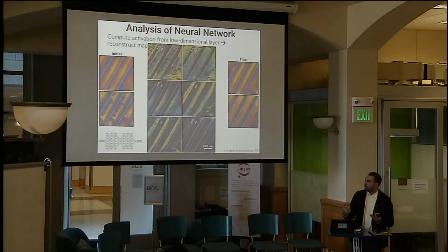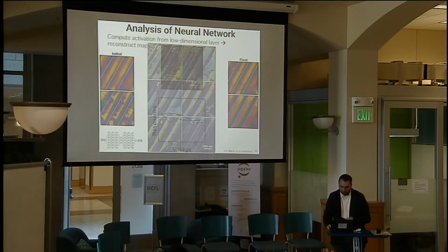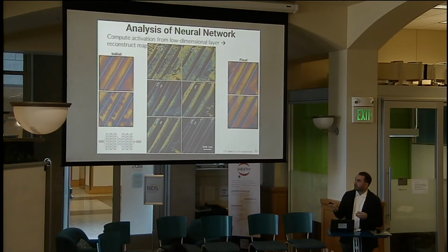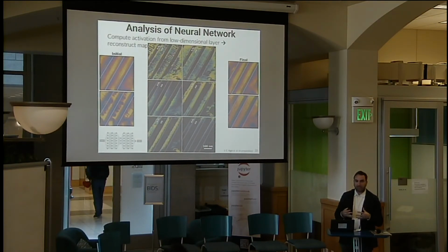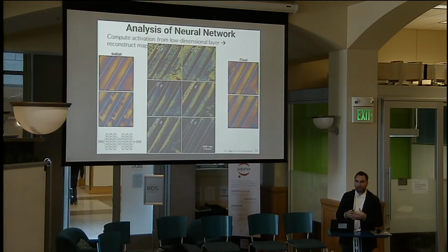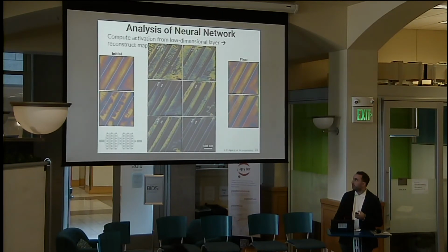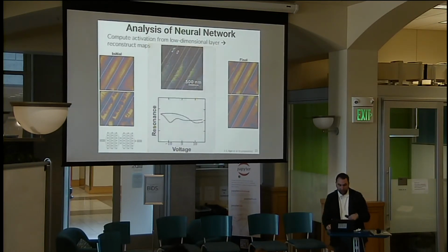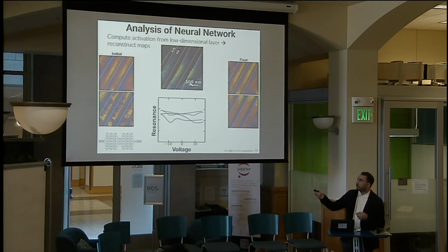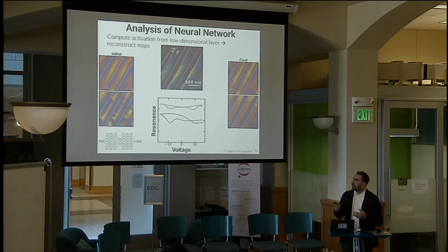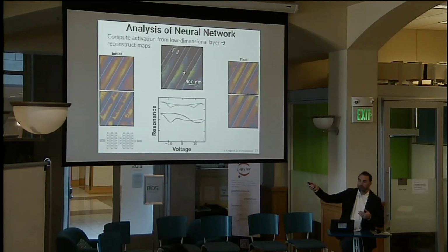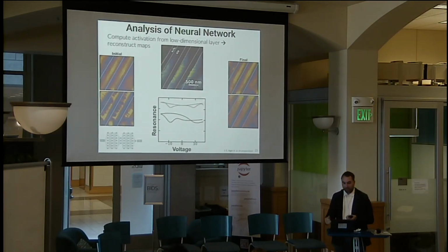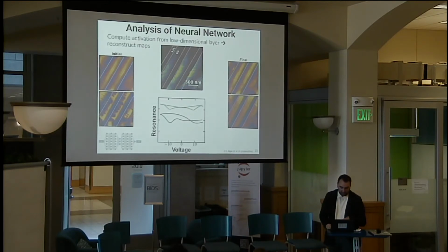I also went on to train this on a more complicated data structure. So this is the resonance response curve, which has a complexity in terms of its functional form that's too complex to even try to analyze using basic empirical models. And again, you can see immediately all the important features related to the domain, to the different structure. And again, the generator showed interesting things that were related back to the physics, like gradients in the degree of response that's related to elastic hardening that we could then back calculate to relate back to the geometry of the material.